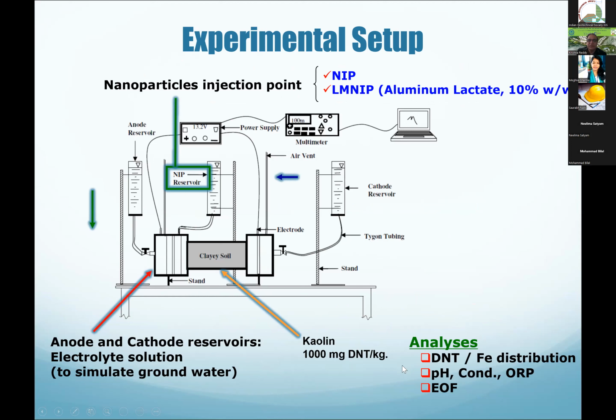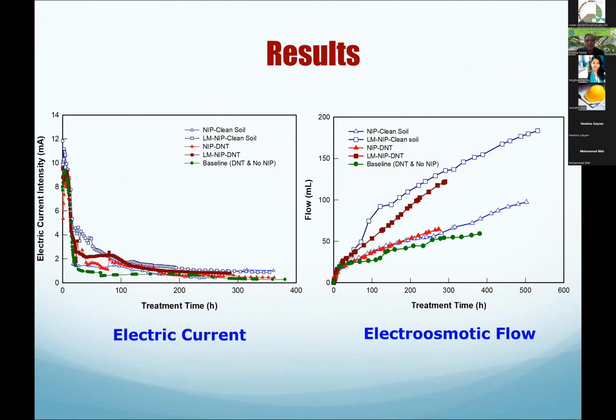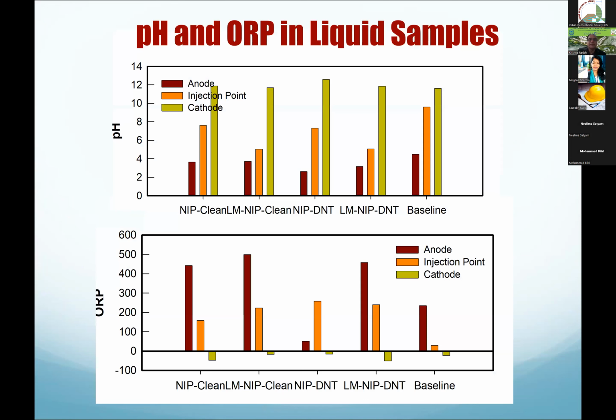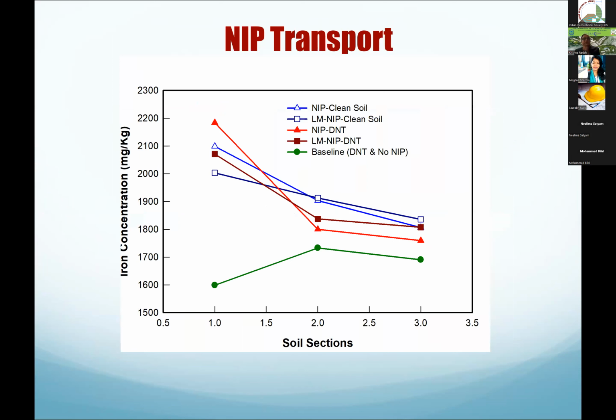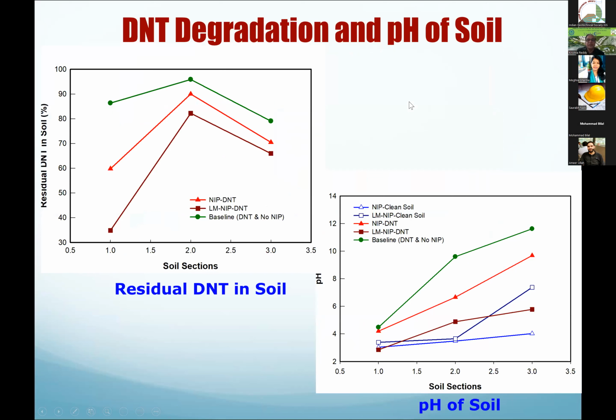We contaminated the clay with the DNT, and we look at the iron distribution, pH, conductivity, ORP, and electroosmotic flow. This is kind of a setup, and we can see the electric current variation, electroosmotic flow variation, and then how the pH changes, and then what happens to the transport, right? You can see a substantial amount of nano iron particles getting transported through these soil sections. And so you can look at the residual DNT concentration, how much is reduced.